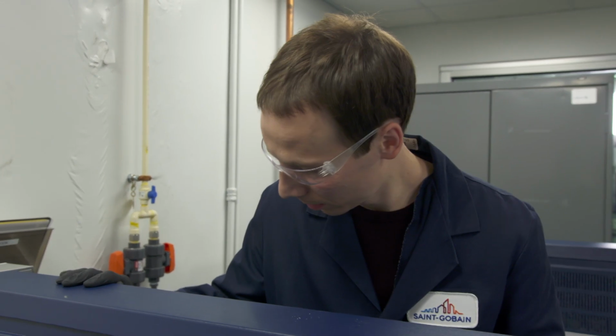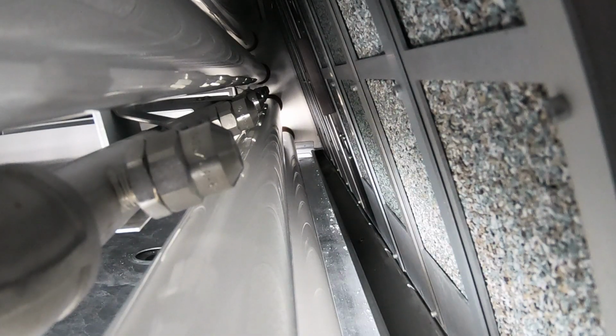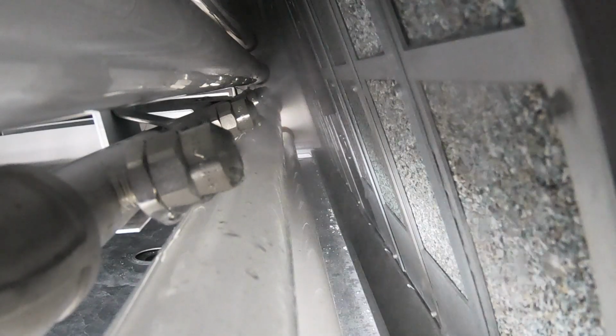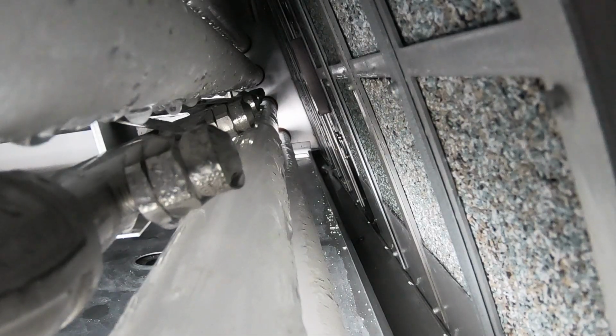Then the lights are going to come off. We're going to actually put a mist onto the sample. That mist adds moisture to the sample as part of the degradation, but also a thermal shock onto these samples that they would experience in a natural environment, to really get that realistic condition. Then after the spray cycle, the equipment's going to have a heated water pan to put moisture or condensation onto the samples, which simulates having dew on a sample in the morning. That moisture effect onto the sample.